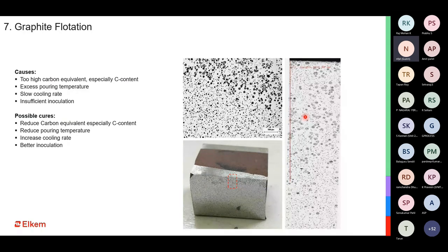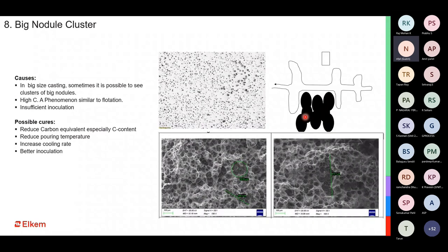How do you control it? You control it, one, by controlling the carbon equivalent, that is most important. And then you can also control it by increasing the rate of solidification, providing chills, etc. And thereby also, if you are able to improve the graphitization potential so that you are able to trap the carbon at different locations, which can be done by improving the inoculation, that could be one of the ways to control the graphite flotation problems.